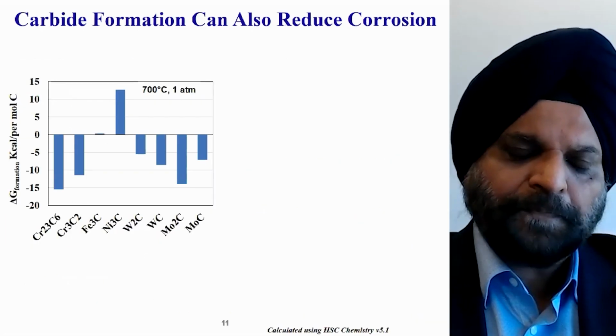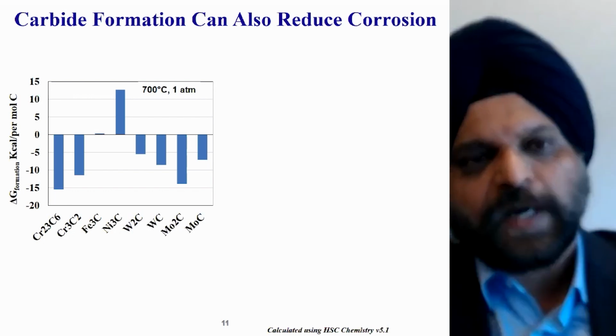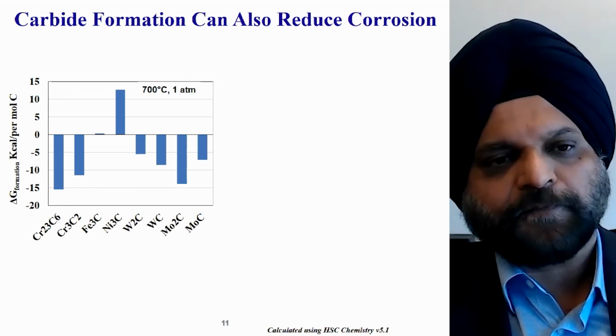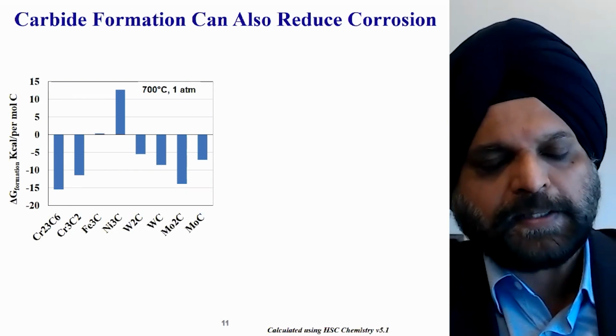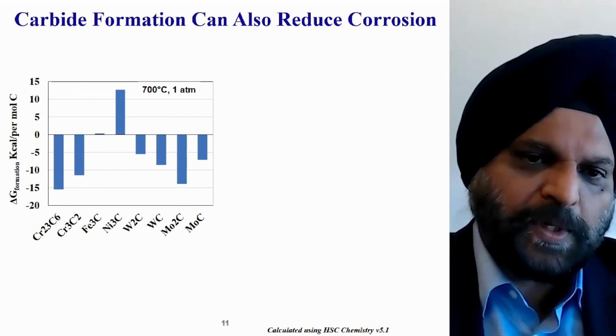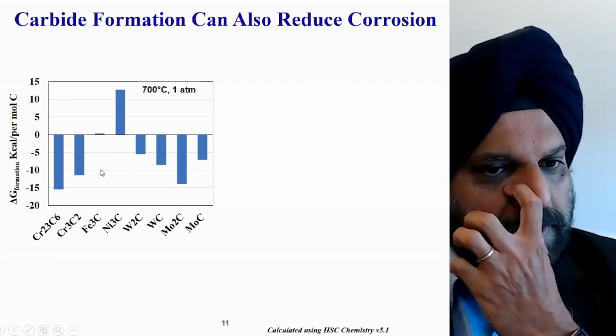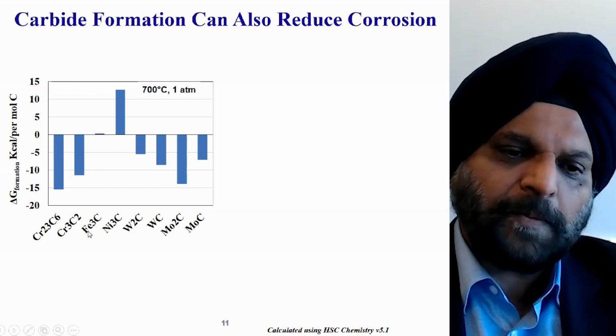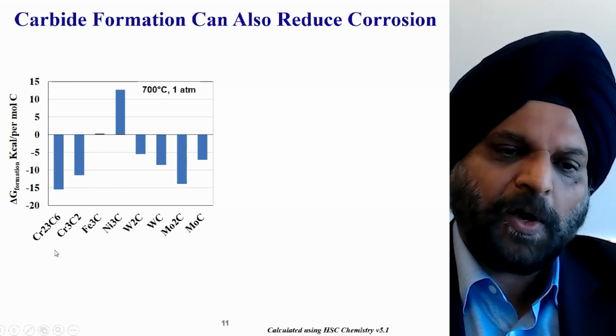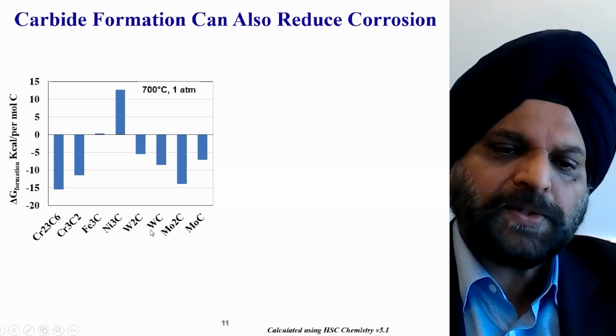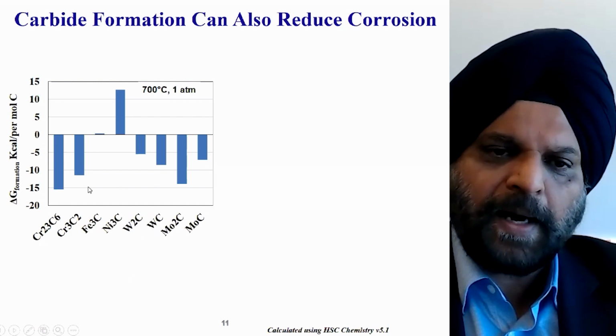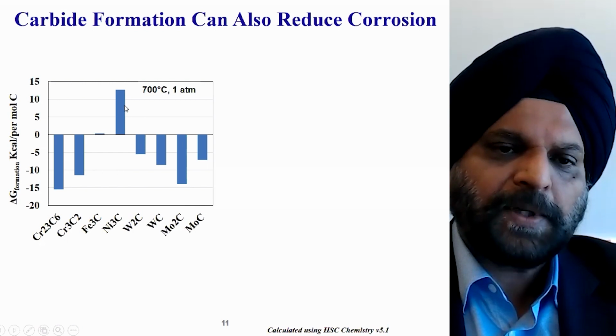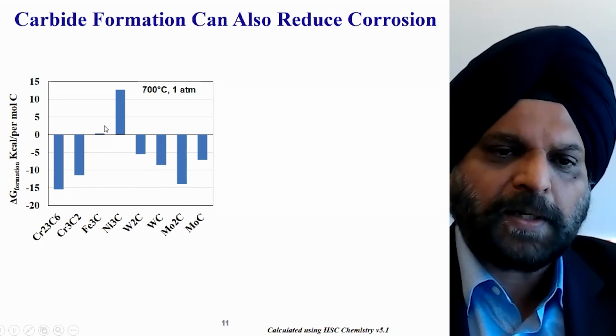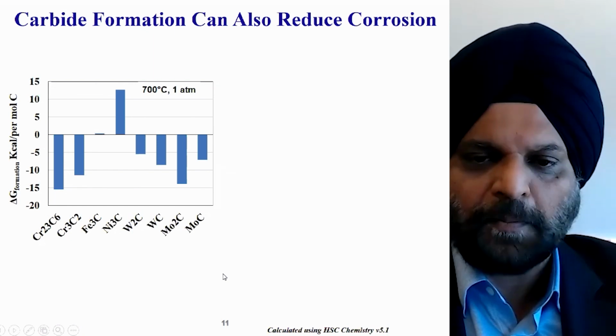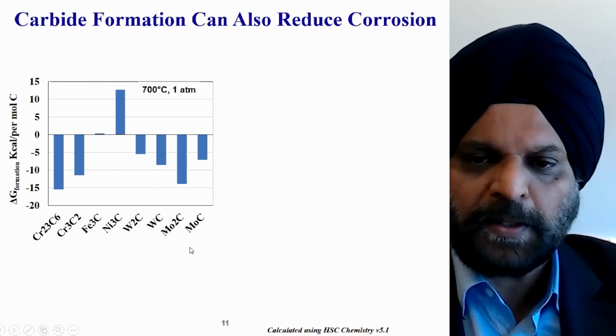But we wanted to see if graphite can eventually have other unintended consequences as well. So if you look at the Gibbs free energy of formation of carbides, we find that from alloying elements, chromium, tungsten, moly, they readily form carbides, whereas nickel and iron are relatively, nickel especially is immune, but iron carbide driving force is more positive under conditions that we consider.